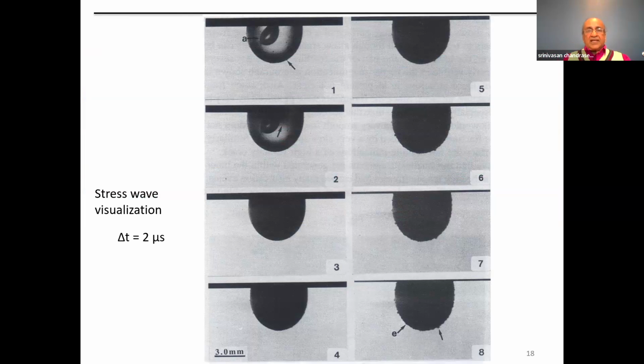Now, there are some other questions one may raise. One may say, well, you set an explosion in motion. Were there some stress waves that were set up in the glass that resulted in the fracture and not this phenomenon of a crack propagating from the tail? So here what we did was we did this experiment under water. So the drop's head is seen under water.